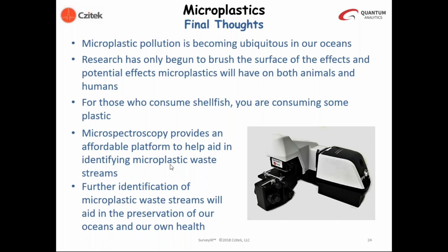But with the ATR device, we've attempted to eliminate some of the steps. In the case of ATR, the sample path length is determined by the ATR element and the optical properties of the sample, so you don't have to thin it. It removes one of those sample preparation steps. And with some of the microplastics, we're actually able to analyze them directly on the filter selectively, so they don't even have to be removed from the filter or substrate. To get back to your question, maybe 5 minutes of sample preparation and a couple minutes of data collection at the max.